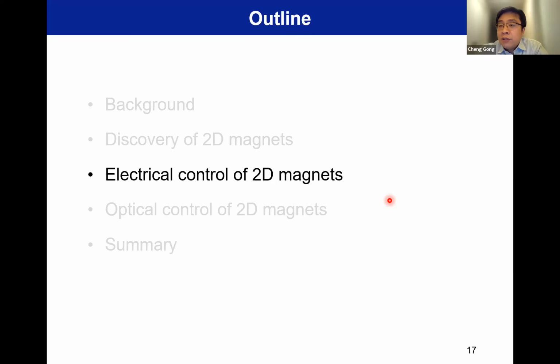So for voltage control, when you do experiment, there are roughly two types of commonly used control. One is you apply an electric field, pure electric field. That's the electric field control. The other one is you use a transistor structure. You apply the gate voltage on the source and drain electrode with respect to the ground. So you have electrostatic doping control. But either way, we will see it's very hard to get efficient control, because if you use electrostatic doping control through silicon oxide, likely you can only control the carrier concentration between 10^12, maybe close to 10^13 carriers per centimeter square.